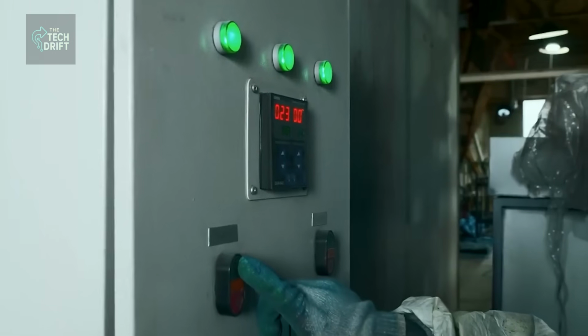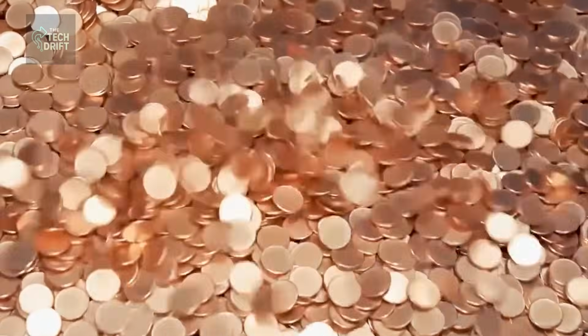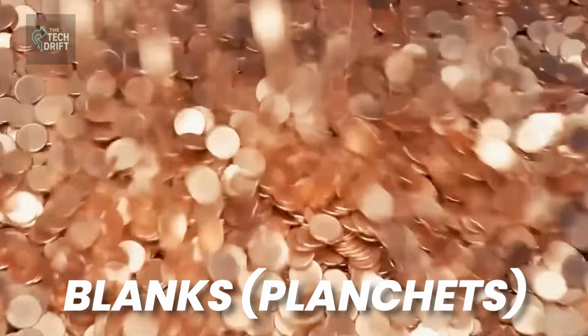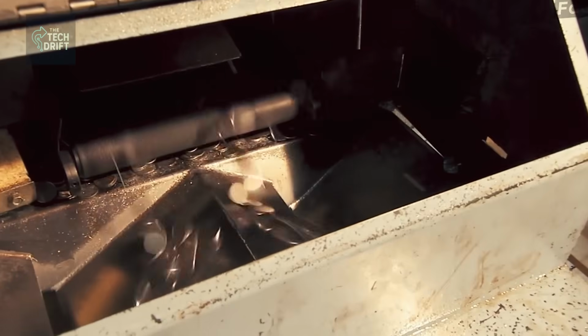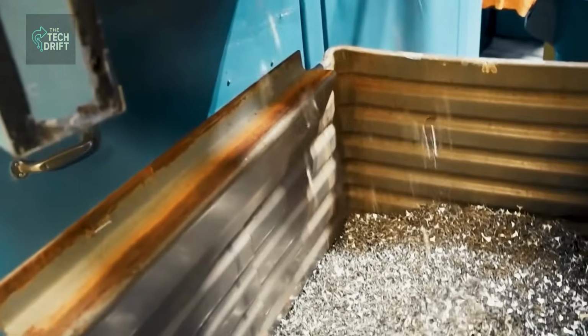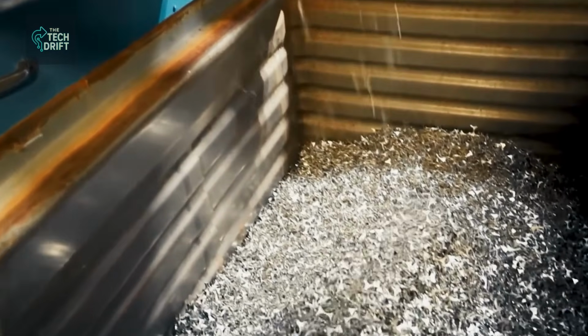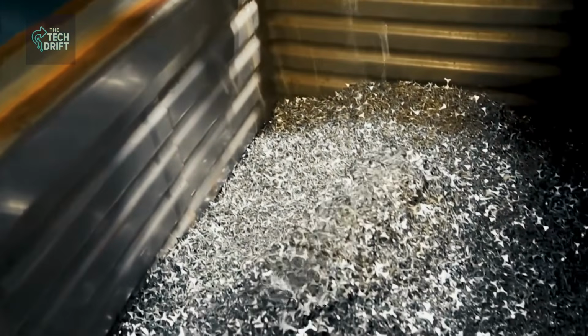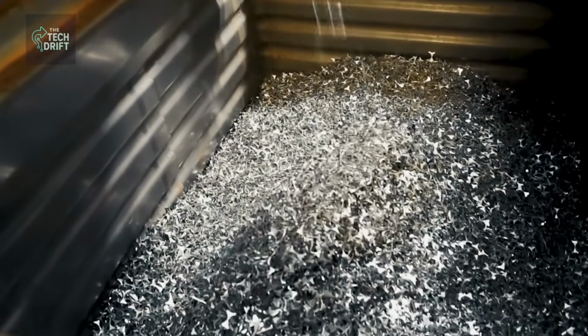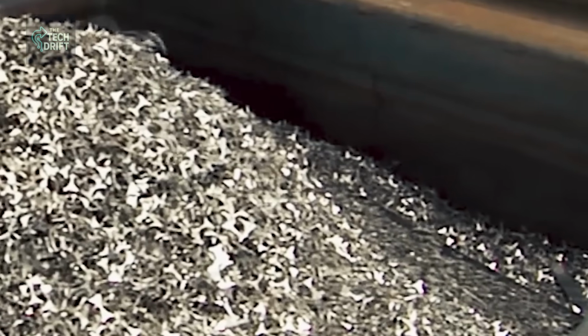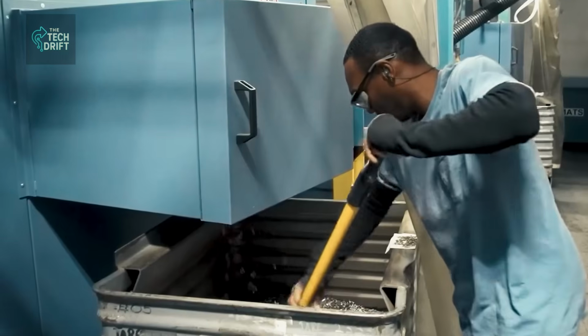First up is a high-speed punch that stamps smooth discs from the strip, known as blanks, or planchets. Think of it as a pastry cutter, only much bigger on an industrial scale. It produces around 14,000 coins per minute, and you can hear the bins fill in a sharp, rhythmic clatter. Punching discs out of the metal ribbon leaves behind a lacy, irregular skeleton the mint calls webbing. Crews rake these jagged offcuts into bins. Then the scrap is shredded and recycled, sending usable metal back into the supply stream instead of wasting it.